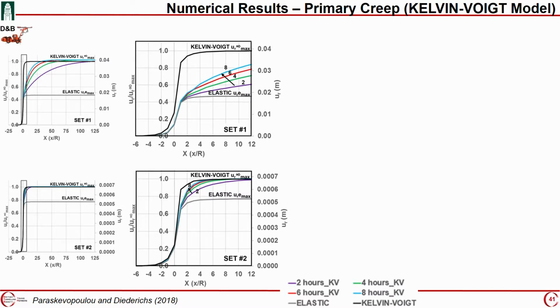They refer to numbers 2 to 8, and they refer to hours. So this is the whole tunnel excavation and support cycle, and the duration was 2 hours, 4 hours, 6 hours, 8 hours. The two sets of parameters, with this retardation parameter one order of difference, can be seen here. What this tells us is that the higher the retardation time, or this ratio, it converges sooner to our total deformation, the tunnel wall displacement, than the other set of parameters.